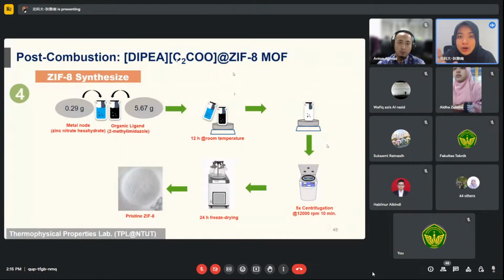Actually, it doesn't increase the solubility in all cases, because at high pressure, the pristine, pure ZIF8 is still better than when we combine. But at low pressure, it's better to use the ionic liquid encapsulated with the ZIF8. So this is the way we use zinc nitrate hexahydrate with 2-methylimidazole. This is the organic ligand and metal node basically.